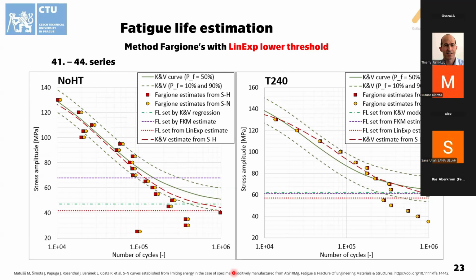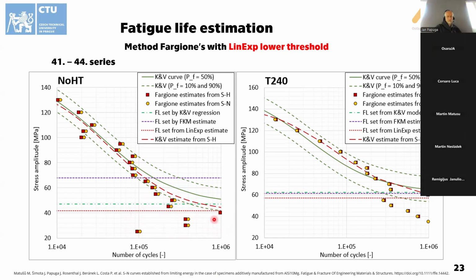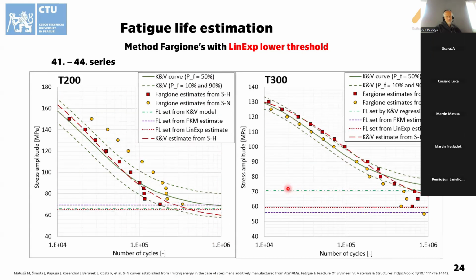So when we are using the LinExp approach as a lower threshold, you can see the results here. Basically, we are eliminating the part of the Fargione's prediction that is not really related to the SN curve at all, and by this we were able to get really good results, as I would say. Sometimes it's not really conservative, but it always fits in the band of 10% to 90% probability of failure. And here you can see the FKM guideline. In some ways the FKM guideline works well, but sometimes it does not, which is problematic. For the T200 and T300 it works as well.